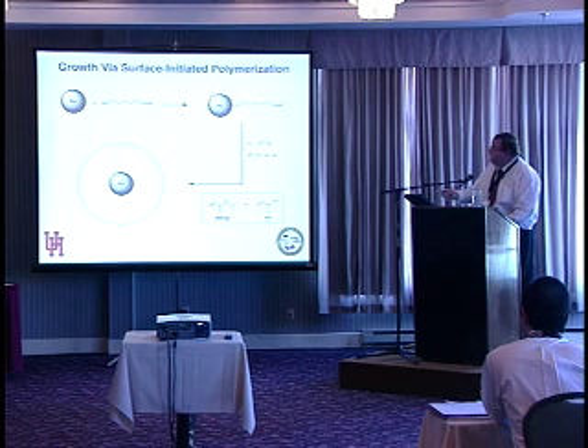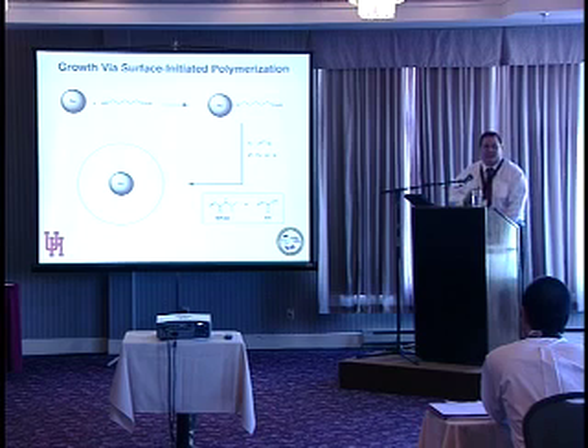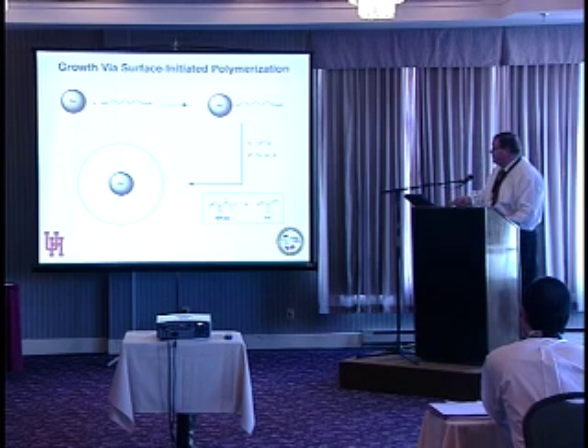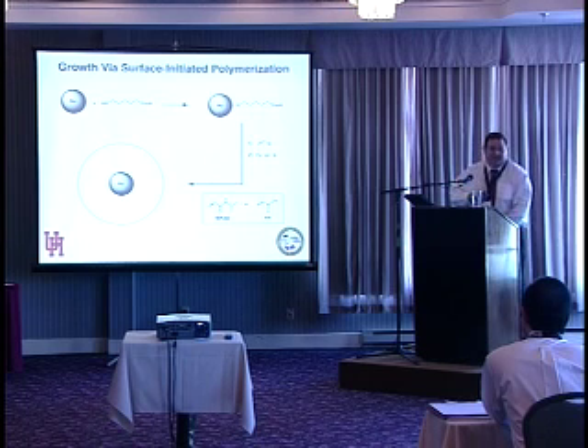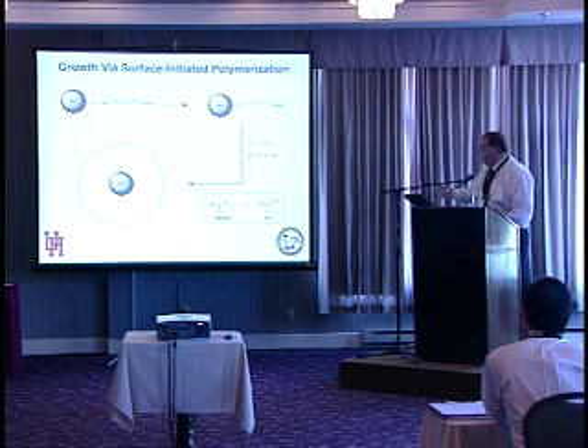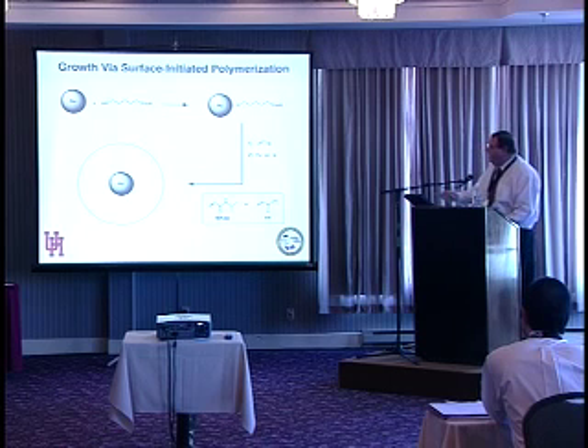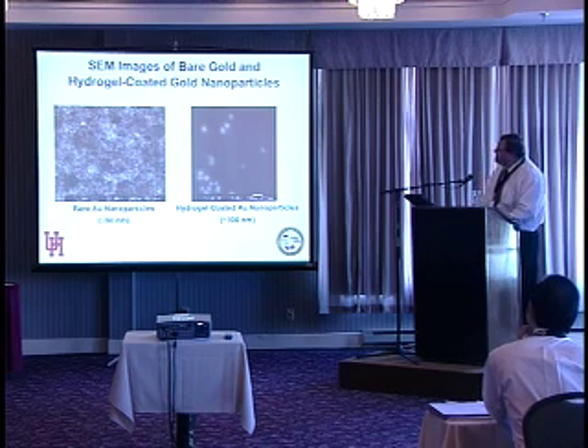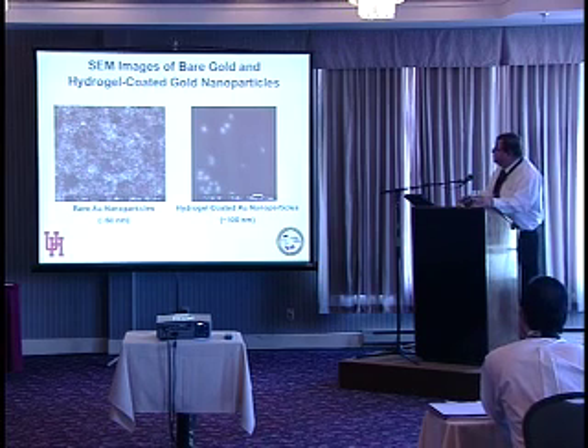And in our research, what we're doing is we're taking the metal nanoparticle and we're treating it with a polymer initiator we put on the surface, and then we add our monomers. Usually, most of the work that we've done so far is using polyNIPAM or a copolymer of polyNIPAM and acrylic acid, which allows us to have a hydrogel that collapses just above physiologic temperature. And so we then do this polymerization and form our hydrogel-coated nanoparticles. And so here are some SEM images of some of the particles that we made.